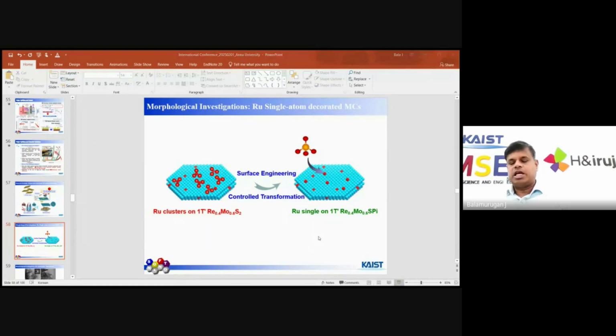And from the strategy, we recently found this mechanism, but this is unpublished work. But with this one, when we go for high loading of single atoms, there is one issue. Single atoms should be bonded with some non-metallic bonding, like sulfur, not bonded with metal bonding like metal clusters. Because each single atom provides active sites, yes, we need to load the single atoms at a higher loading, then only can we get higher performance.